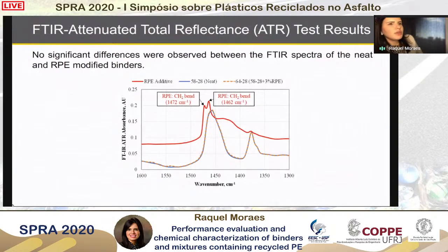Then we start to evaluate the chemical characteristics of these binders. The first test was the infrared using ATR, attenuated total reflectance, where the materials are evaluated in the solid state without addition of solvent. And we can see here, by the overlap of the lines of the neat binder and the neat binder modified with 3% of recycled polyethylene, we couldn't capture a significant difference between the neat and modified with recycled plastics.